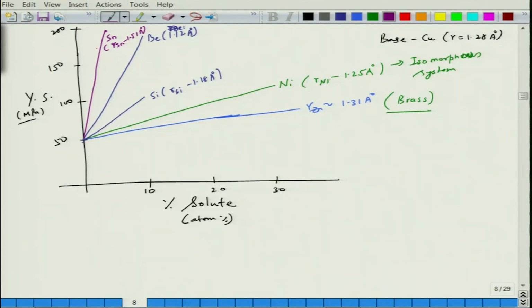So you can see the predominant effect. You can add a little bit of tin to copper and increase the strength from 50 to nearly 200 megapascal, a 4 times increase in the strength. You do not have to add a lot of tin to it. And tin, however, has a larger size as compared to copper, so you can't add a lot of tin. Zinc, on the other hand, gives you solubility of about 25-30%. You can look at the phase diagram for the range, but it does a fair bit of strengthening from 50 to, let us say, about 70 MPa. Nickel does the strengthening all the way, and nickel can increase the strength by about 100 megapascal or so.